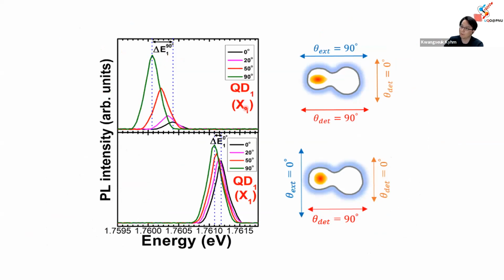Okay, for example, exciton 1 from here, under H or 90 degree excitation, we detect from 0 to 90, like that. So from this result, you can imagine the shape of the wave function. For example, here, 90, it's a large confinement size, so it's a low energy. Okay, here. And large oscillator strength, so the intensity is a bit large. On the other hand, 0, the small size and confinement is large, so high energy, and the intensity is small.